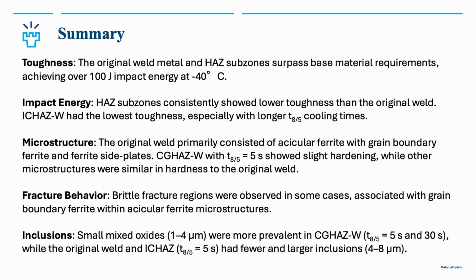And regarding fracture behavior, the brittle fracture was connected to regions where we had grain boundary ferrite. And as you saw, the inclusion results were quite interesting. There were a lot of small inclusions in coarse-grained heat affected zones.